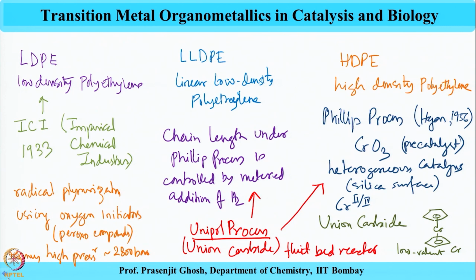So, what we see if we sum up is that there are several industrial processes involved for producing various grades of polyethylene. To start with, it was the ICI, or Imperial Chemical Industries. Currently, radical polymerization is also used with oxygen initiators for producing LDPE, low density polyethylene. For HDPE, it was a heterogeneous chromium trioxide process in the 50s called the Phillips process, which was producing HDPE, and then Union Carbide comes into play and produces HDPE with chromocene, which is a low valent chromium precursor, and finally, by